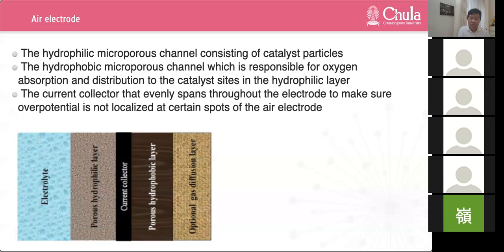And PTFE is the only suitable binder now in the case of zinc air batteries because of its high corrosion resistance in alkaline electrolytes as well as hydrophobic properties. The hydrophobic layer is engineered in such a way to promote maximum gas intake without leading to electrolyte flooding. Electrolyte flooding will prevent oxygen reaching catalyst sites at the hydrophilic microchannel. Current collectors are chosen based on conductivity and stability of a material. And for the current collector, we usually use nickel foam because it has high conductivity and also high corrosion resistance, making it ideal for use at the air electrode.